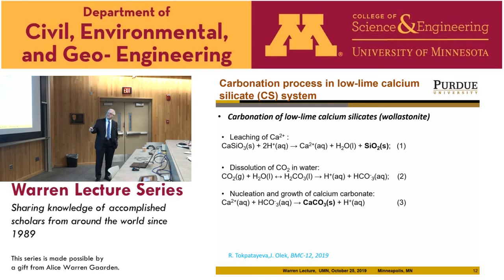CO2 from the atmosphere comes in and creates the carbonate ions. And carbonate ions react with the previously leached Ca and form calcium carbonate. So the circle kind of closes. We decompose limestone, calcium carbonate, to make the cement, and over time we are going back to making artificial limestone. So that gives you an idea that the concrete can actually be a sink, if you will, for CO2, right? You can bind it. That's for regular concrete or regular cement. But if you have different calcium silicates with different ratios of calcium to silica, it's the same process. So non-reactive components of the cement that I was mentioning, they can carbonate the same way.